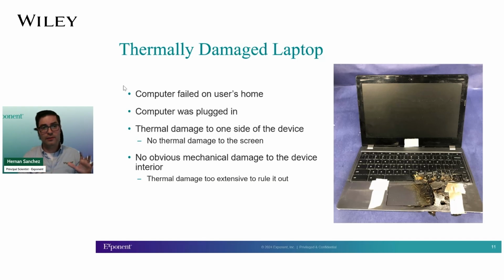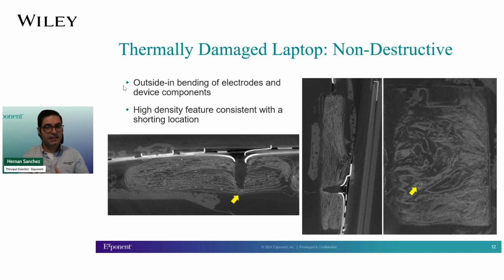And then we were not seeing any obvious mechanical damage to the device interior because there was too much thermal damage. So this is where, once again, with CT scanning, the first thing we do, we gather that data and take a look at what's inside before we do anything destructive or any disassembly. And all of a sudden we saw that there was this outside-in bending of the electrodes and device components coming from the keyboard side of this device. And on top of that, where you see that yellow arrow, you see this high density feature.